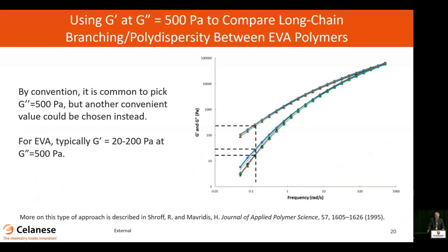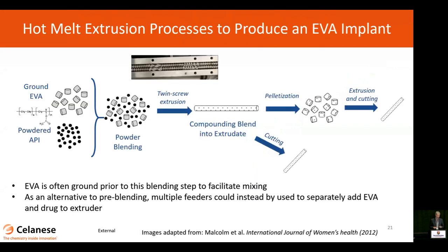So if you look at a measurement like this, you might pick a value of say like 500 pascals for G double prime. And then you could compare the value of G prime at the same frequency across a number of polymers. And then this will give you a very sensitive measurement that can then be used to actually predict some of the other elongational and rheological phenomena that you'll see when you start to actually process the material. So let's talk now why we might care about that.